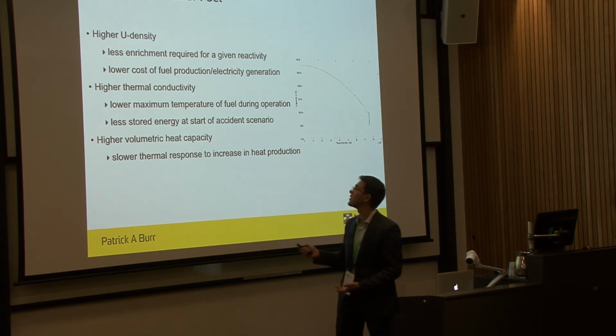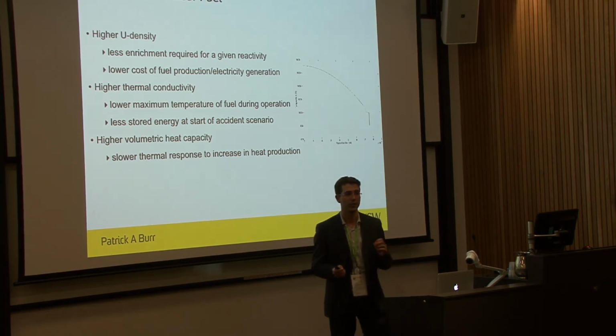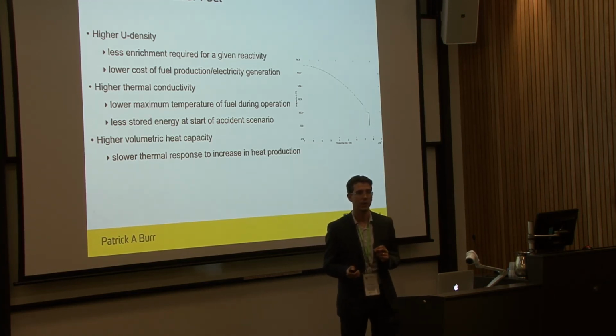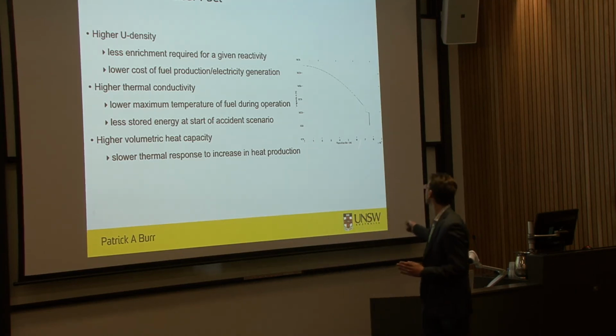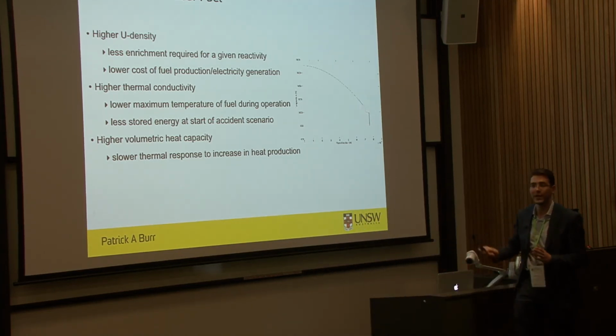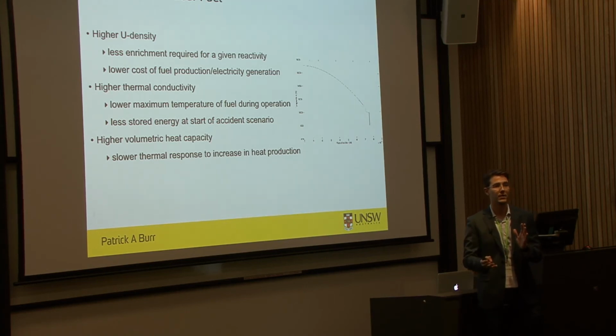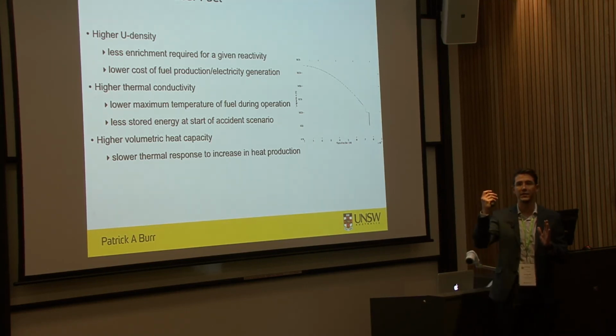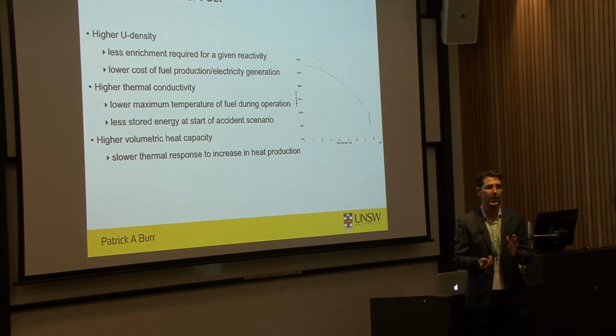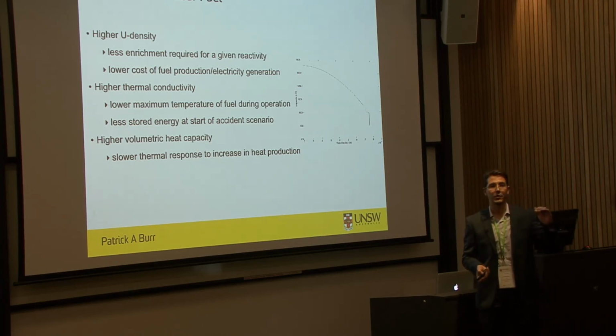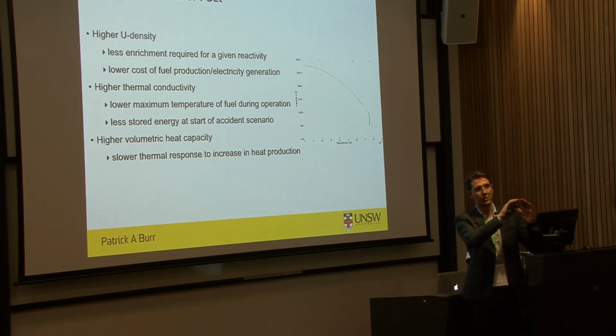You might try, for instance, increasing the thermal conductivity, because that's what decides the maximum temperature inside your fuel. The outside temperature of your fuel pellet is completely governed by the coolant. If your coolant works at 350 degrees C, that's the outside temperature of your cladding. The inside temperature of the fuel is simply dictated by how fast you can move heat from the inside of the fuel to the outside.